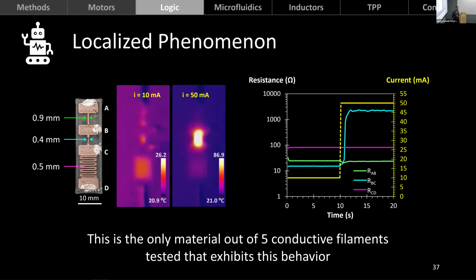And so what do we do with this? Well, we were able to come up with a 3D printed switch. The way we did that was we basically designed two intersecting conductive paths. One from A to B that we used as the power path, and another one, C to D, which we call the control path. And the way this works is if there is no bias applied to the control path, then the